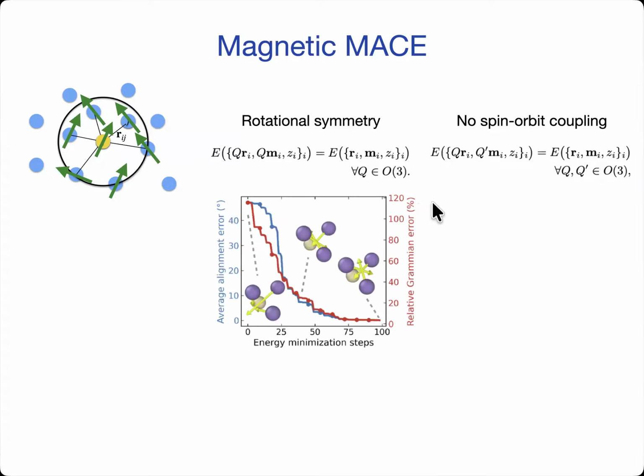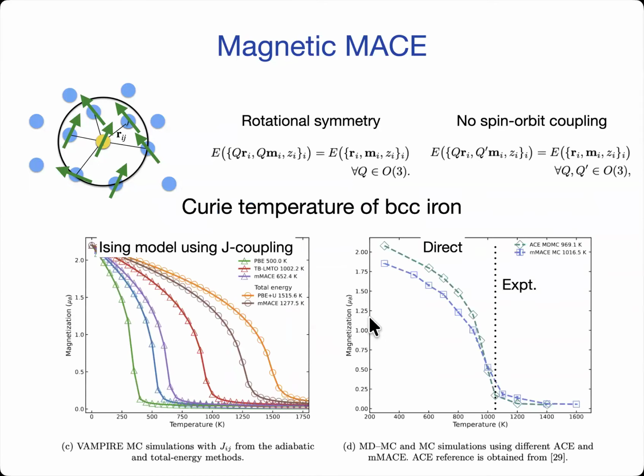And then you can study exotic systems, like here's a manganese platinum, Mn3Pt, and you see the non-collinear spin relaxation, and this is the frustrated magnet, really, and you see this sort of triangular arrangement of spins as you optimize the energy with respect to the spin direction. You can do larger scale simulations like the Curie temperature of iron.